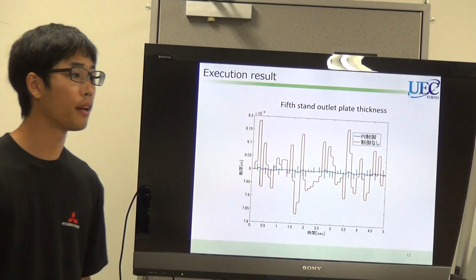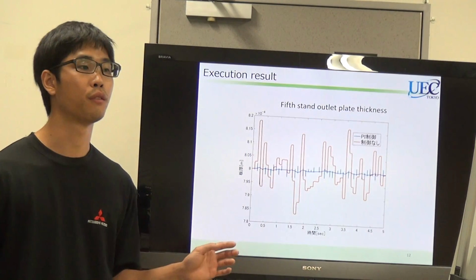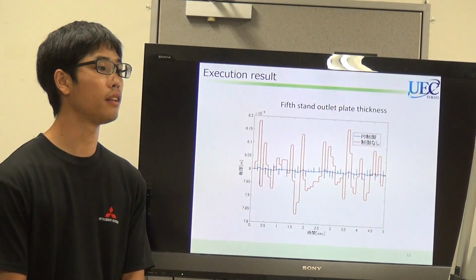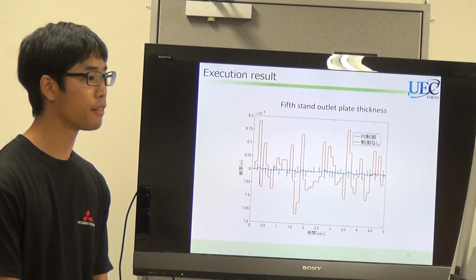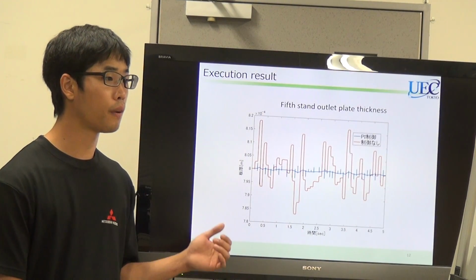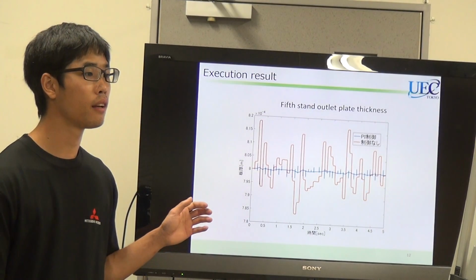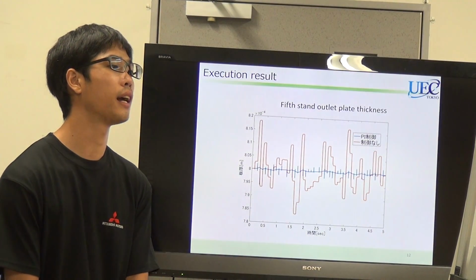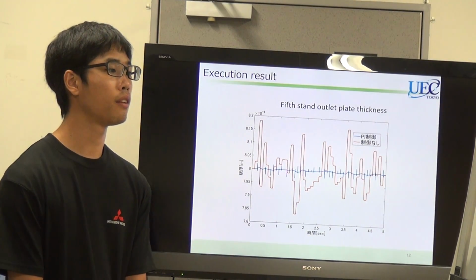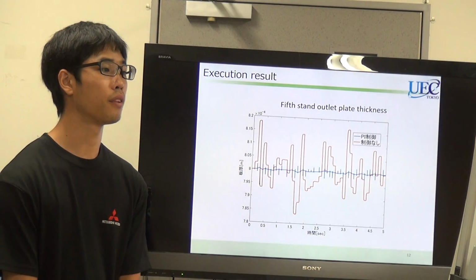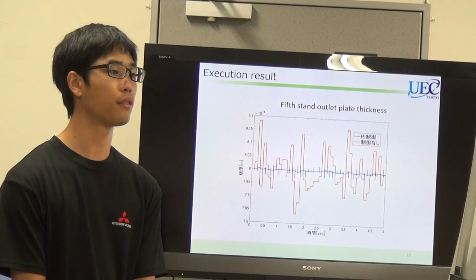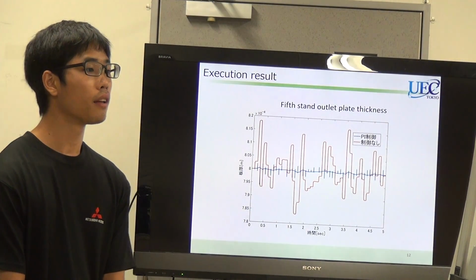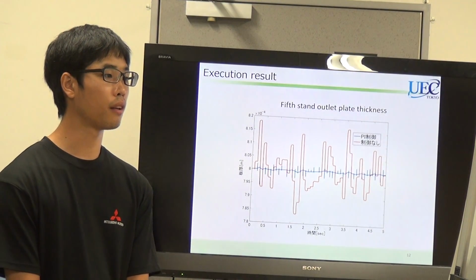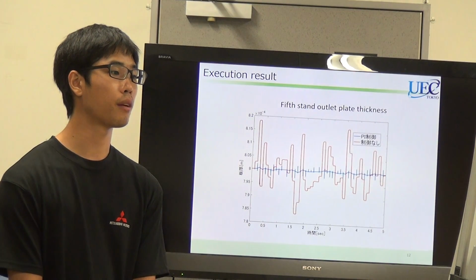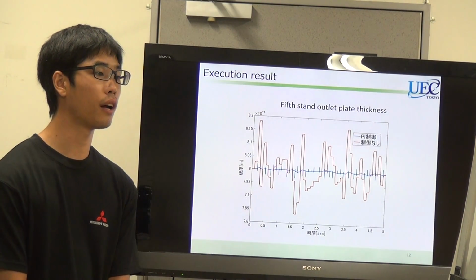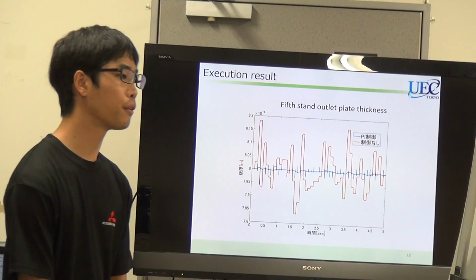Here is the execution result. The line indicated with orange is one without roll control. The line indicated with blue has PI control of the roll. Through those, the thickness of the orange line, which does not have the roll control, is indicated at the final stand exit, while the thickness with the PI control is stable at roughly 0.8 millimeter.